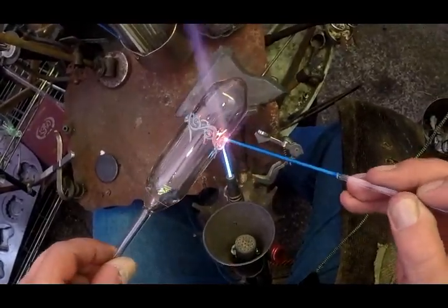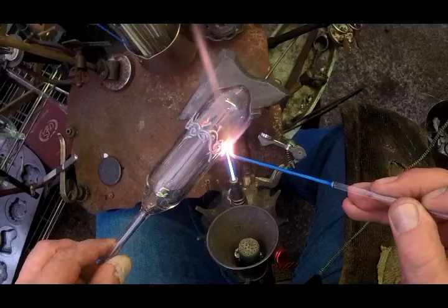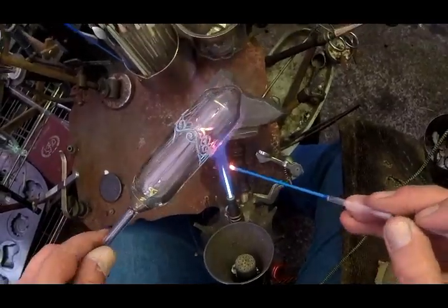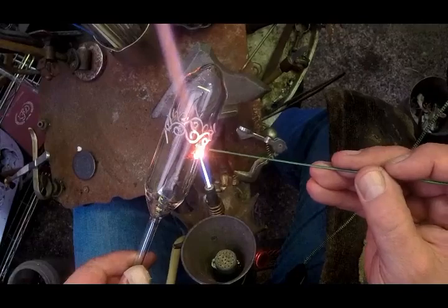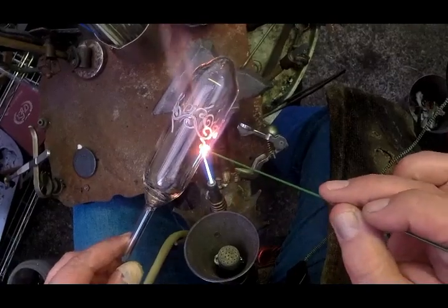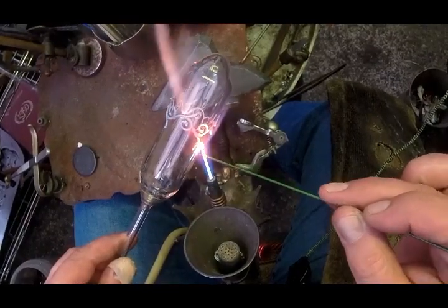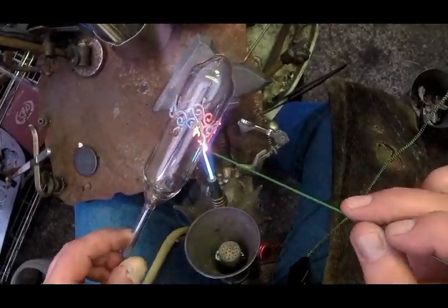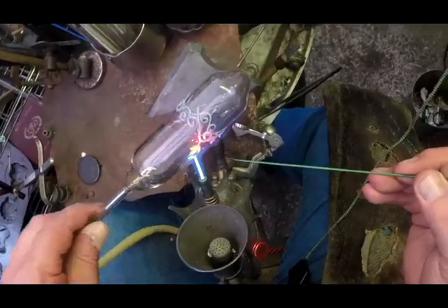Each of these is just a little spur on the vine, and each of those is going to get three little green leaves at the end. Then we'll place parallel rows of amber dots alongside. I'm just heating it up a little bit to keep the whole thing crack-resistant. At the end of each piece as I'm drawing it on, there's a little back-pedal — that prevents creating an acute angle at the tip. Yes, push it forward, but pull it back as you pull it out of the flame, and that backward pull will remove most of your acute angle issues.